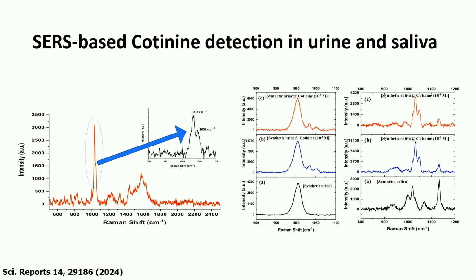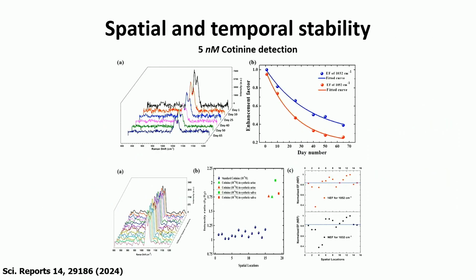So we showed that we can actually have label-free detection of this cotinine, because we don't use one single peak, because it's a broadband response. We look at the multiple peaks, the peak positions as well as the peak height ratios to precisely detect the biomolecule. In this case, it's cotinine. So this again shows the spatiotemporal stabilities. Even after 6 months, we could still get the signals from these samples.